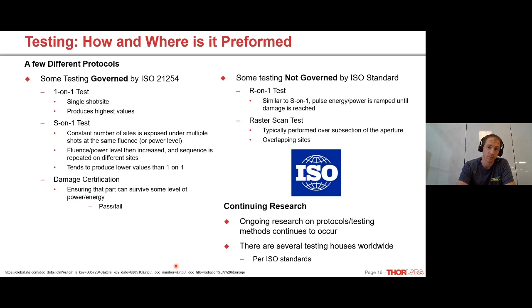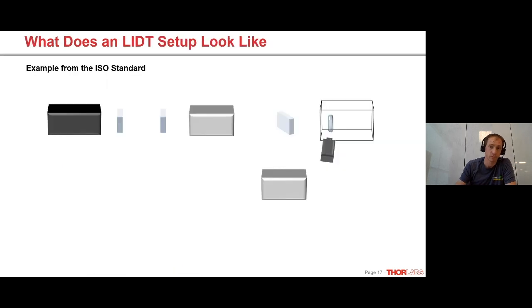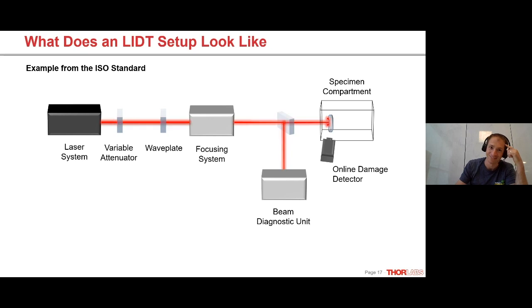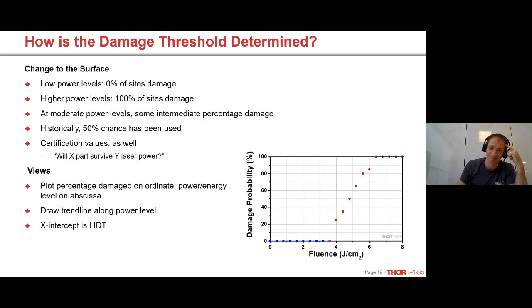Sort of continuing on with that and damage testing. So if your damage probability curve never reaches 100%, let's say some of your points are damaged at a low energy fluence, but then you move up to a higher energy fluence and see nothing damaged, but you never quite hit that 100%. What does that tell you about the damage threshold of your optic?